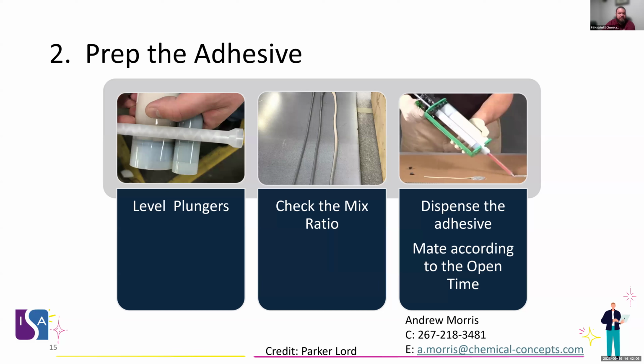Then you want to make sure that you got material dispensing out of the tip. On a piece of cardboard or a piece of blank stock, run out a bead of adhesive about the length of the tip, just to make sure that those two parts you're working with are both dispensing properly. A lot of times you'll notice right at the beginning, like this picture in the middle is showing, that you'll have some discoloration at the very beginning as you start to dispense that material, and then it'll kind of level out to the solid color that the adhesive should be.